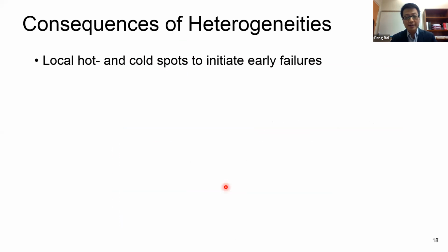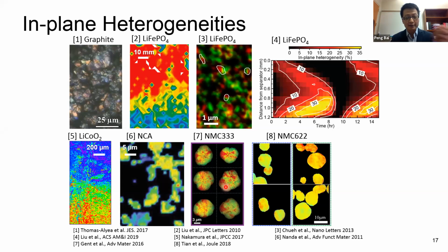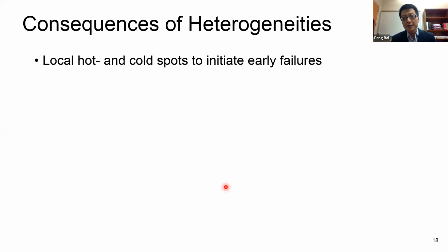So here, when you see this kind of contour, different colors and heat maps, it tells you the level of heterogeneity. And the consequences are many. First, practically, you would easily imagine there are hot and cold spots, right? The hot spots can really become hot because they pass a higher current. And their Joule heating effect, the local heat, can even melt your polymer separator. That's really a safety threat. But when you have cold spots, that means some amount of material did not participate in the reaction. So you waste the material, compromising your energy density. That's not what we want, right?